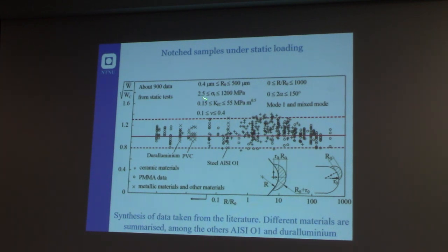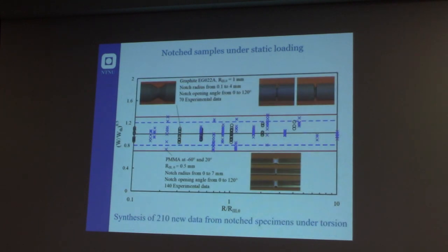Actually, the ultimate strength of the material ranged from 2.5 to 1,200 megapascals, so from a very soft polymer to almost an ultra-strong steel, with a fracture toughness ranging from 0.15 to 55 megapascal times square root of meters. So a large variation. Mode 1 and mixed mode loads were included in this database. So the results were quite good.